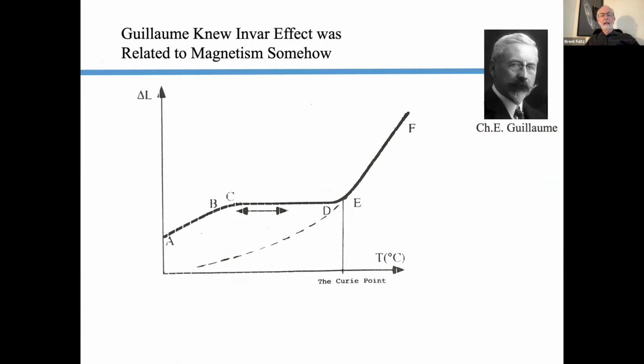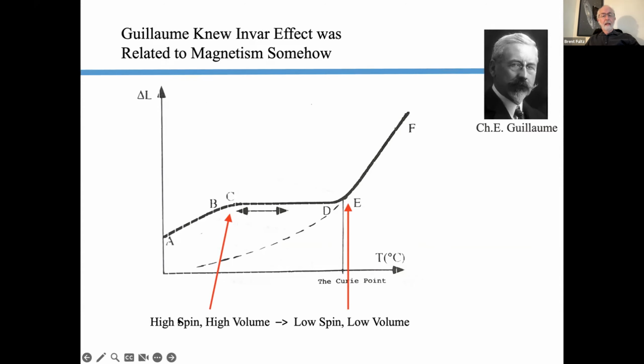And here's a plot of the length of the sample versus temperature. The part up here at high temperatures is pretty normal, and that's the expansion he expected. At low temperature, the expansion gets smaller, but this flat part he knew was associated with a Curie transition, a magnetic transition. So this led to a large number, hundreds, maybe thousands of papers to relate the magnetic behavior, which has a high spin at low temperatures, and it loses its orientation with temperature, as magnetism does. But this also has a high volume.